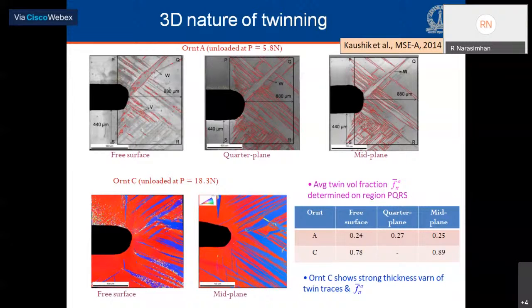We quantified the average twin volume fraction by marking out a rectangular region PQRS, as I've shown in this diagram, about 900 microns in size, and then used ImageJ software to quantify the twin areas, then calculated the average twin area fraction. And in the table at the bottom, if you examine that table, you can see that at this stage, there is not much dependence on the thickness as far as the twin area fraction is concerned for this orientation, around 25% everywhere.